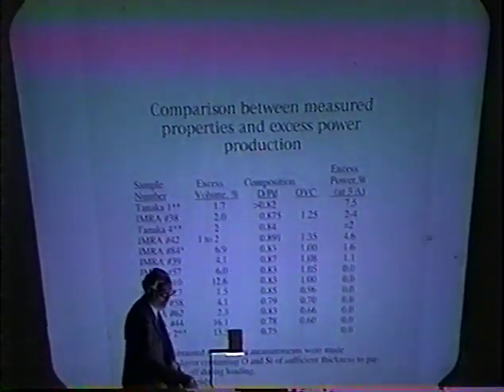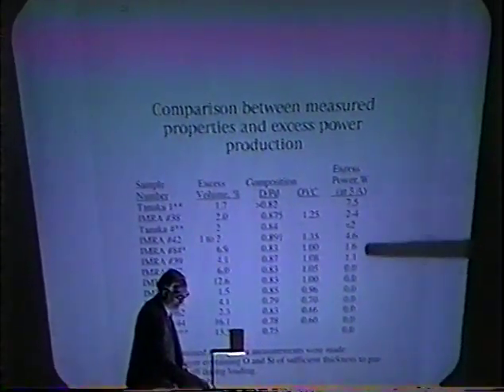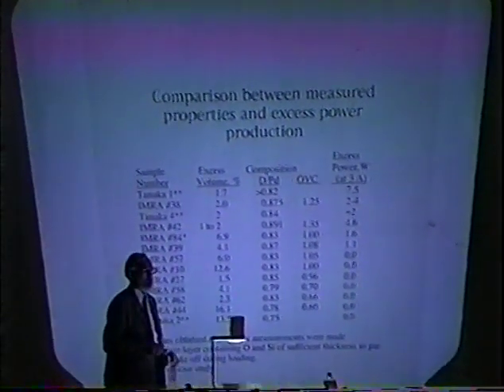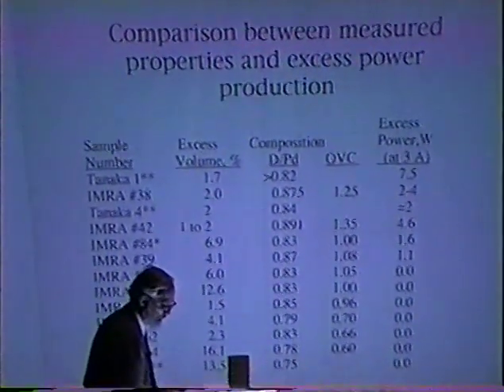Now, I won't have time to show you the calorimetry and the heat measurements. Please be assured that I have gone to some trouble to do accurate calorimetry. I have samples that have made excess energy. Here's a list of the various ones showing how the excess energy relates to these various parameters that I was measuring. And just as a general trend, you can see that those that have a very low excess volume are the ones that are making excess energy. Those that have a high excess volume are not. There's a few exceptions in there for various reasons.